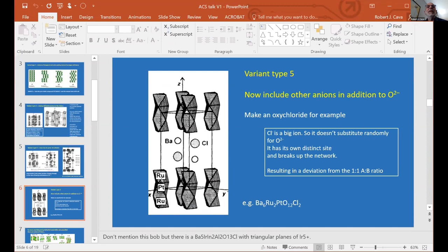But the trimer is basically a chain that's broken up by the fact that you have barium chloride layers in there. You can have a barium chloride layer, but that thing being so big, the chlorine being so big, means that it doesn't mix with oxygen and it forms in a distinct layer.